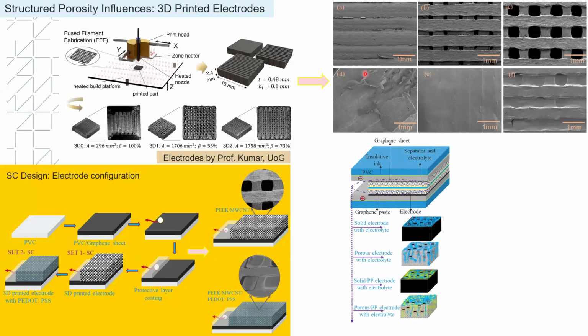What will happen is that when you drop an electrolyte, the electrolyte is mainly reacting on the surface, meaning all the surface where the electrochemical reaction is happening, which is the electrochemical active surface area. This is one of the most important parameters in electrochemical capacitors. But when we have a porous structure, the ions or the electrolyte diffuse inside the porous structure, enhancing the electrochemical active area.